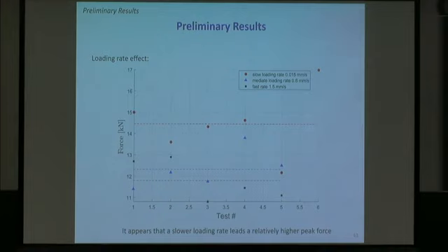But what's puzzling me is that in addition to directly loading and splitting it, we also did some other tests. We loaded up the sample, but we didn't load it until it fractures. We stop, we hold, and then wait for a while. The load drops very fast. We wait until the load drops about half. Then we keep loading it up, and then stop, and the load drops because we have displacement control. So once we stop our engine, the measured force drops. So we go through several cycles.